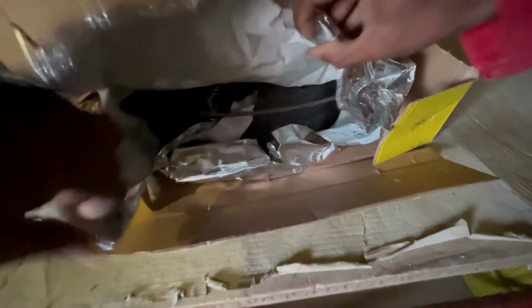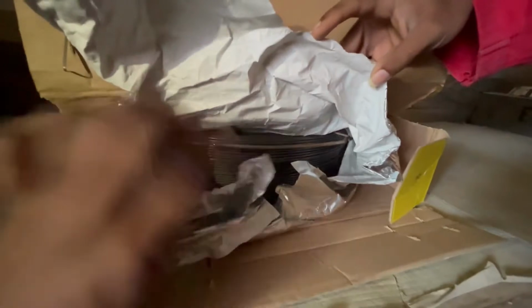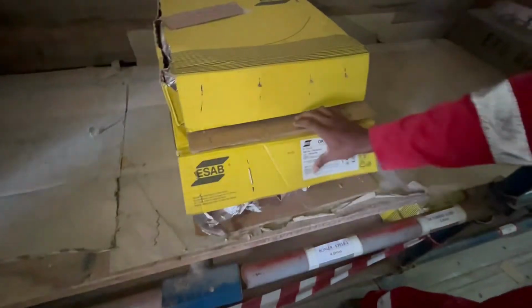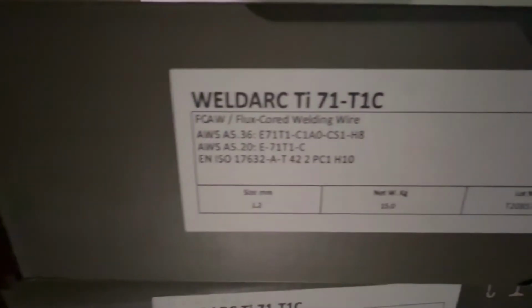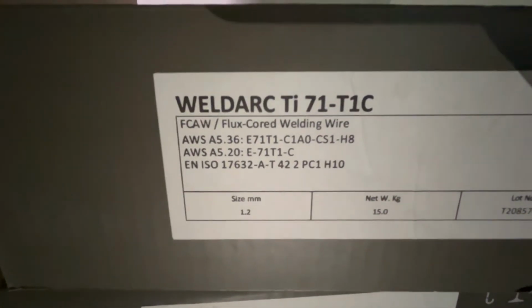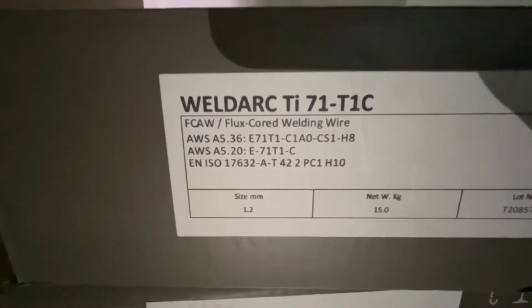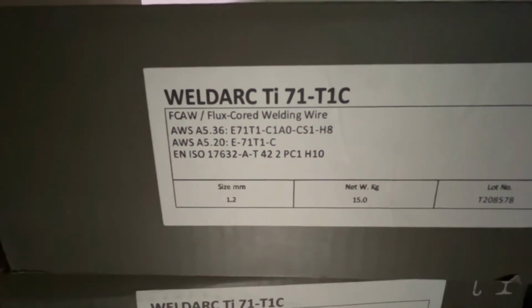For example, this 1.2 mm FCAW wire, this wire has come back with this seal, but the seal was broken. It was used, some part of it was used and then returned to the store. So that information is also required to be logged in the format and then kept very nicely so that it will not corrode. So these are the flux core welding wires, the Weldarc, which we use, 71T1C. This also you can see is returned, and both new and returned are kept here.